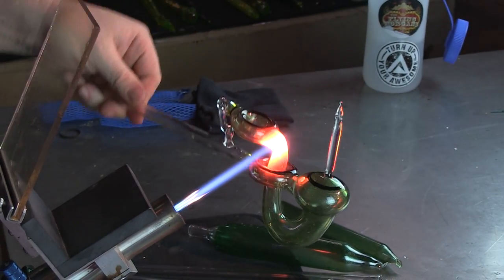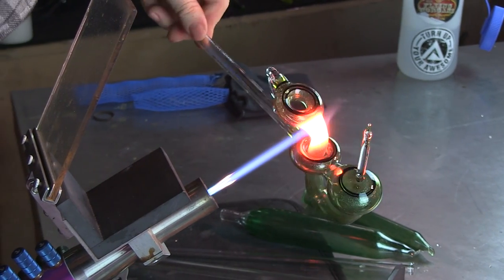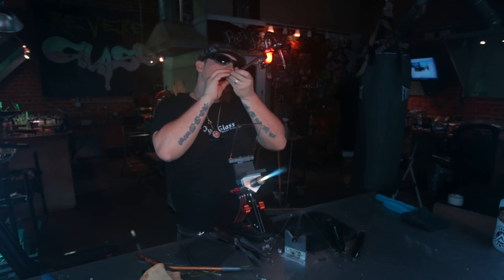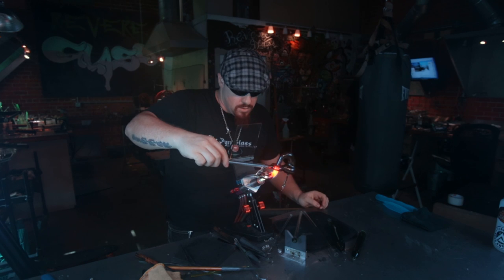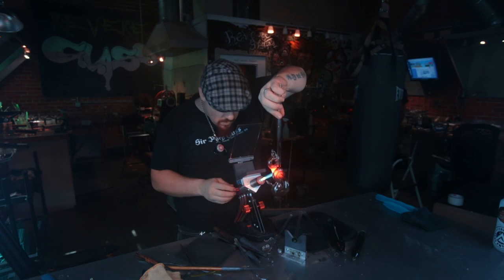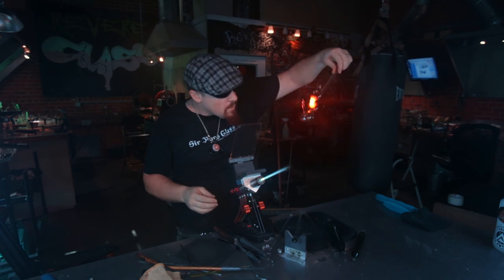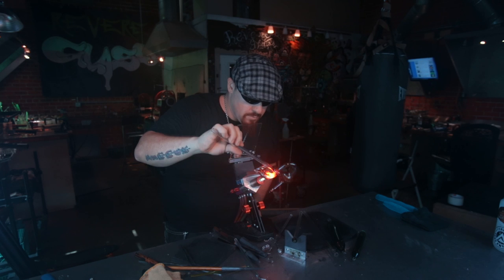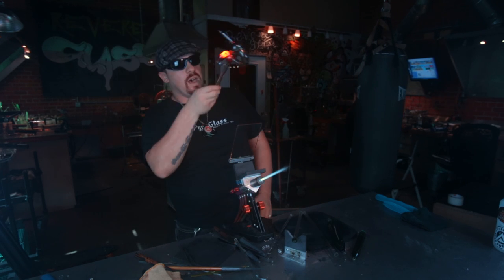The hardest part about doing this point is getting your flame control just right, because you are heating up the inside of the donut. You have to be really careful that your donut's really consistent and it's not going to crack, or that your donut's not going to blow out and stick to the side of your penetration tube. So just put that in the kiln for about 10 minutes and then let that settle up. We can go work on the other parts.